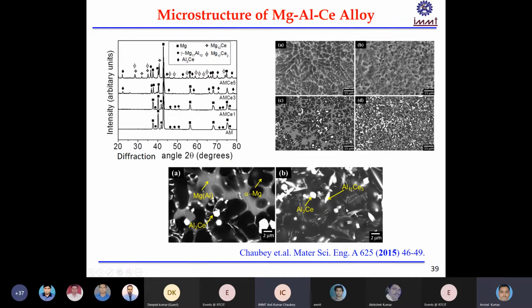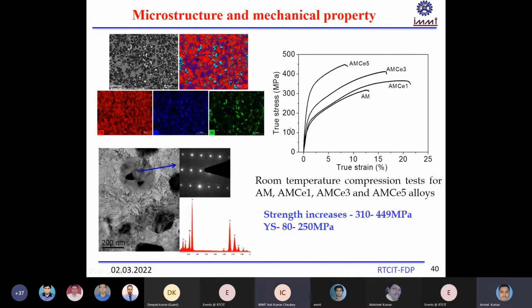So in case of the high percentage of the cerium, you can see the phases distribution in this image, and after that here you can see the mechanical property. This is the magnesium aluminium alloy, this magnesium 10 aluminium, and this is 1 cerium, 3 cerium, and 5 cerium. So you can see that by adding cerium, you can improve this strength.